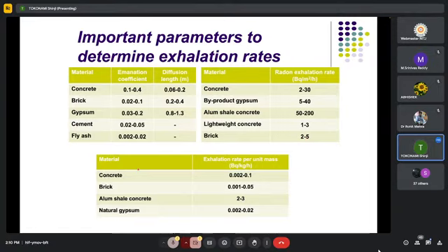Here is a table on the various materials and mass exhalation rate expressed in becquerel per kilogram per hour. The concrete 0.002 to 0.1. The brick 0.001 to 0.05. Alum shale concrete 2 to 3. Natural gypsum 0.002 to 0.02.